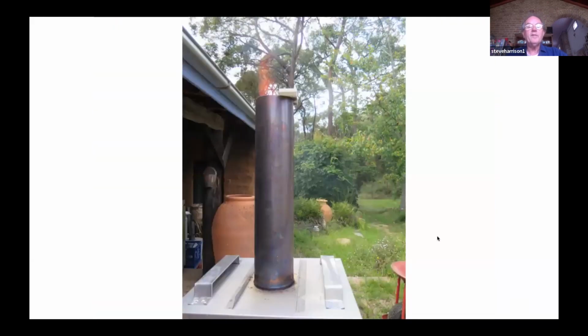So there's a little bit of a flame coming out there. This is in the reduction phase. So you can see there's a tile on top of the chimney. We've put a little brick slither there, and you can damper the chimney back to get more intense reduction if you want to, and to slow the kiln down. If you want to go for, say, 5 hours instead of 3, you have to slow it down by closing off the damper a little bit. Next one.